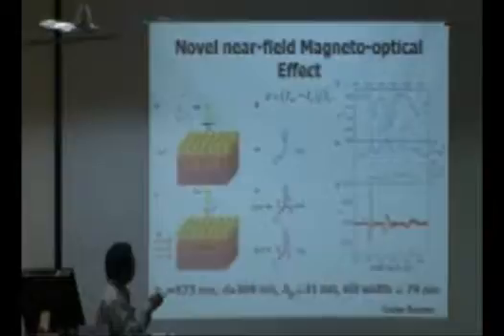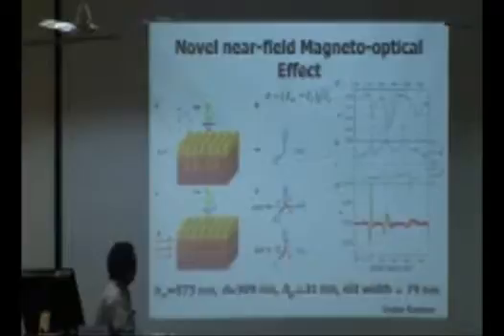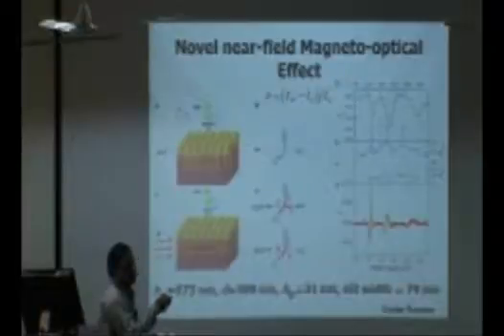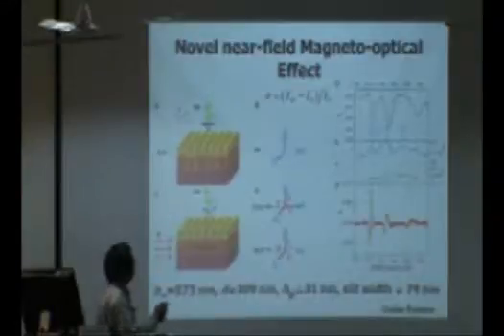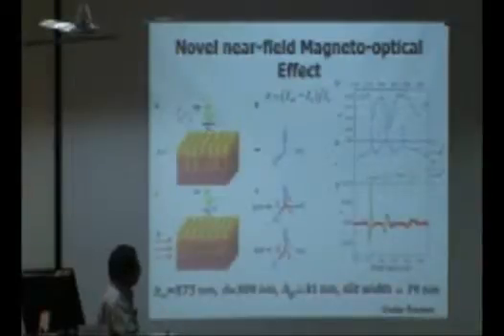So the result is that you have these TE-like fields which are available in the TM mode, and the TM-like fields which are available in the TE mode resonances. So if we design our structure so that we have both TM and TE modes possible, then there is the possibility of coupling TM to TE mode or TE to TM mode. So what we show here is basically this function delta, which is defined here. There is an S-polarized light component which is enhanced in the transmission in the far field. Okay, when the TM and TE modes are resonant, there is an enhancement in the transmission for the TE component in the far field.